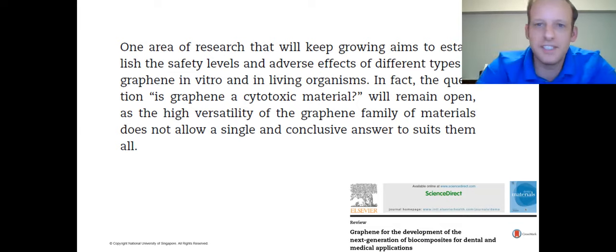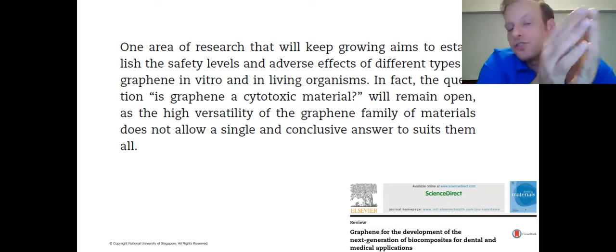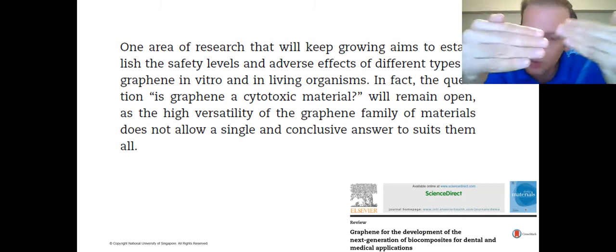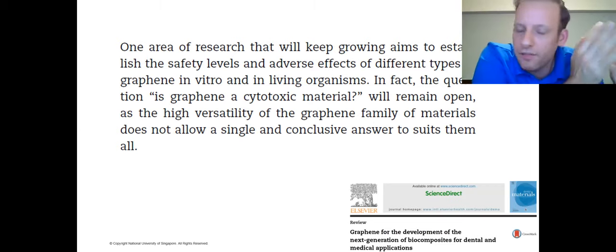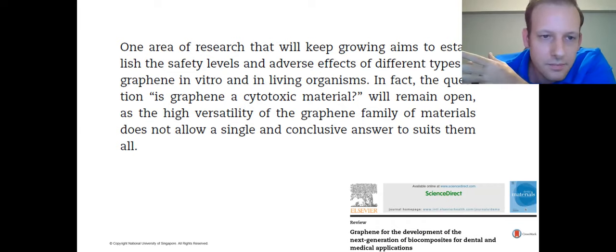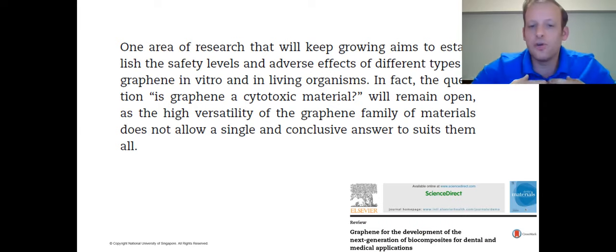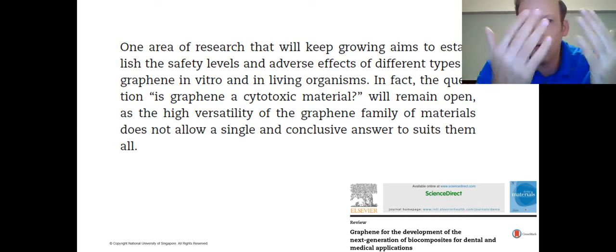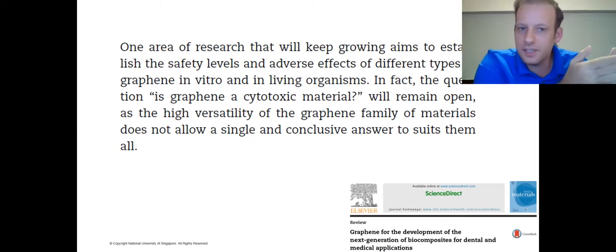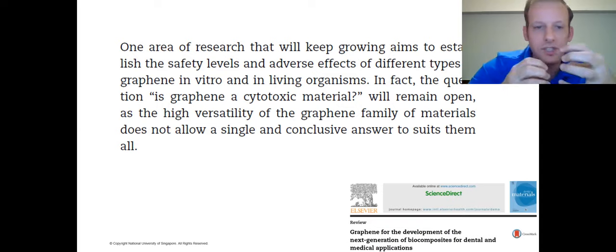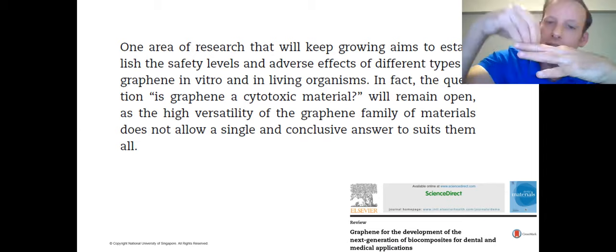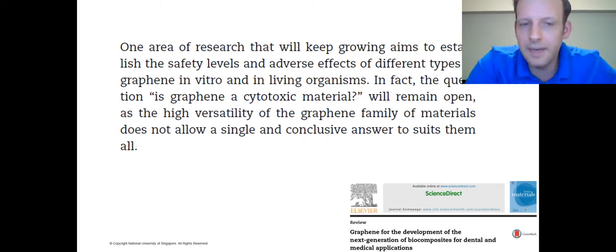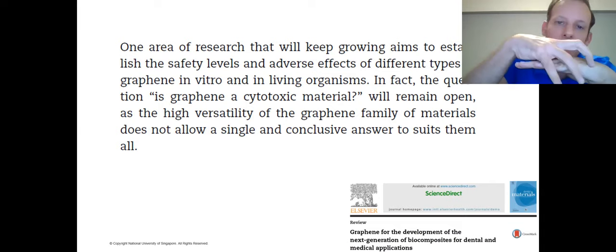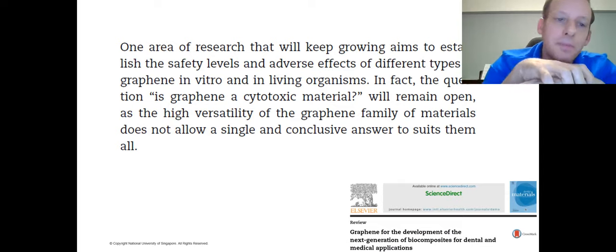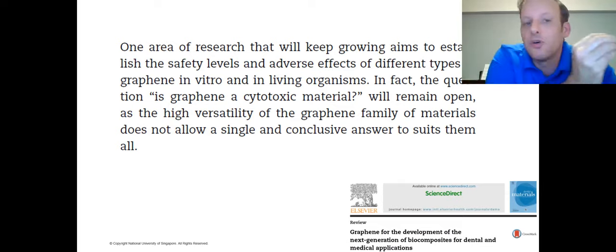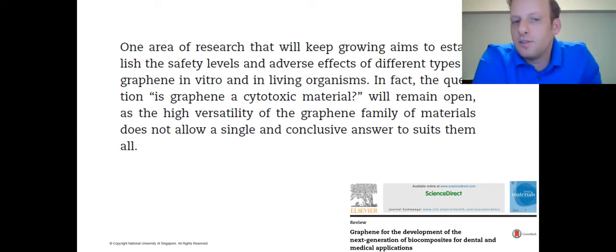So if you think about, for instance, diamonds and asbestos, they are both made of carbon in their structure. But nobody dies because of diamonds, and lots of people die because of asbestos. So you cannot think about the cytocompatibility of graphene without thinking about what you are using graphene for. For instance, of course, if you have graphene nanoparticles in suspension, these nanoparticles will enter the cell and maybe they will kill the cell. But if you use a graphene coating that cells are not able to absorb, and even if they absorb it, it's not at the nanometric scale, maybe you will not have problems with cytotoxicity.